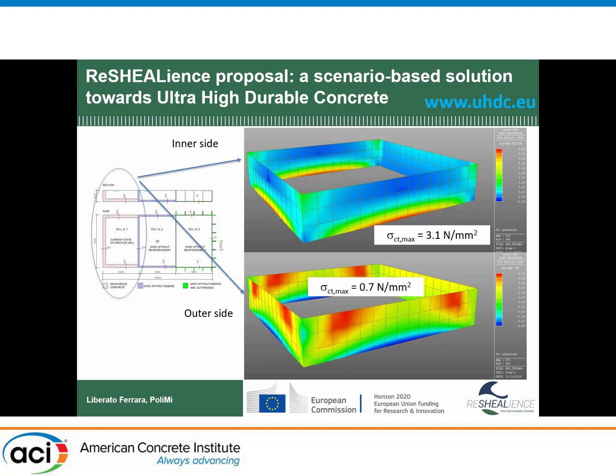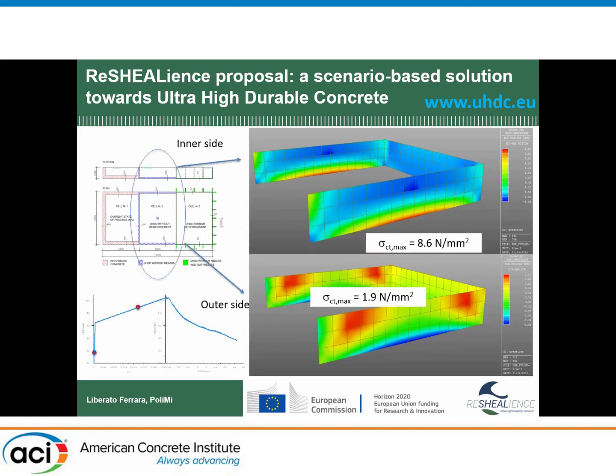for the regular concrete. We proposed the solution of simply using the better performance of the material. You can go down to a 6 centimeter thick wall. So the saving on the material is about 6 to 1, and you just compensate all the costs. But then, you see these are the stresses that we got, and compared to the constitutive curve, we are here. So we are in the hardening stage, and we are at about 0.5% of strain, which could be a little bit too much in the serviceability limit state, but it's still in the range the material can sustain.